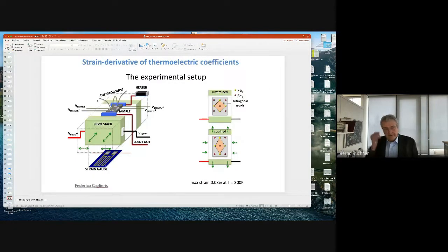And I have still a couple of minutes, so I will also show you other measurements which you can do. It's also a very exceptional situation. What we also did now, in order to understand in more detail the Fermi surface, or the anomalous Fermi surface due to these nematic fluctuations, we did measurements of transport coefficients like thermopower and Nernst effect as a function of strain. So we took again a piezo stack, glued the sample on top of that, applied a voltage, applied a temperature gradient, and measured the longitudinal and transversal voltages.